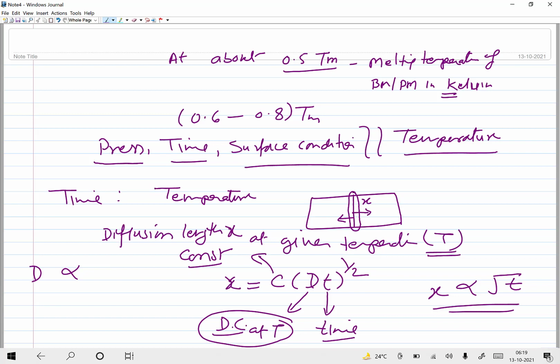So basically the diffusion based reactions change in proportion to the square root of the time, and this variation is exponential as a function of temperature. So these two things will bring in the significant change, and this relationship also speaks about the relative influence of the diffusion temperature and the diffusion bonding time.